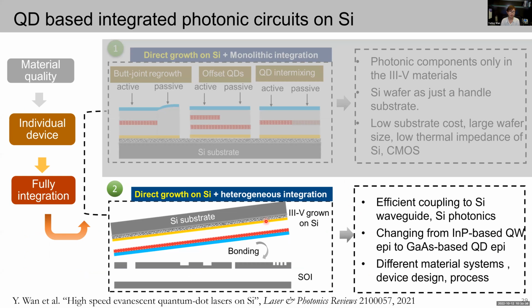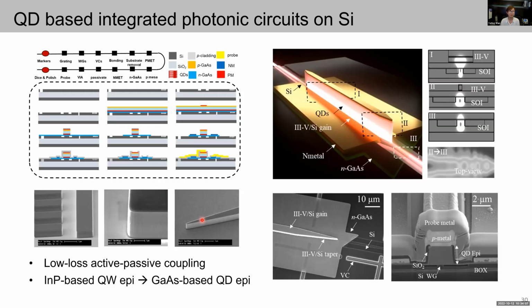low-loss active-passive coupling of III-V with the silicon waveguide. And this is something we really call silicon photonics. In this case, compared to the standard heterogeneous process, it requires a change from the indium phosphide-based quantum well epi to gallium arsenide quantum dot epi. And thus, we need different material systems and thus different device design and process optimization. So here is the schematic showing the quantum dot laser integrated on the SOI substrate, which consists of this hybrid III-V silicon active region coupled to the passive silicon waveguides by both ends.